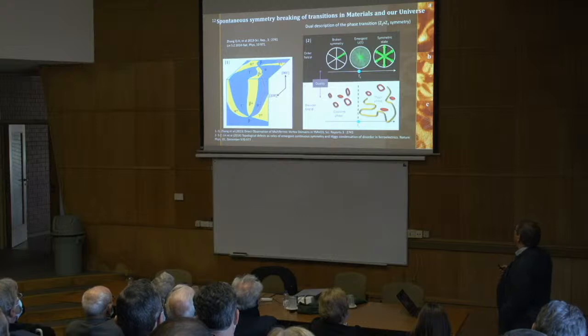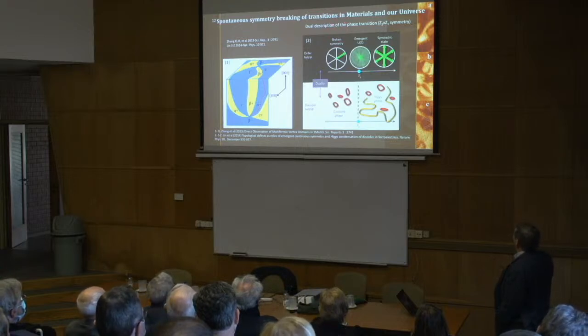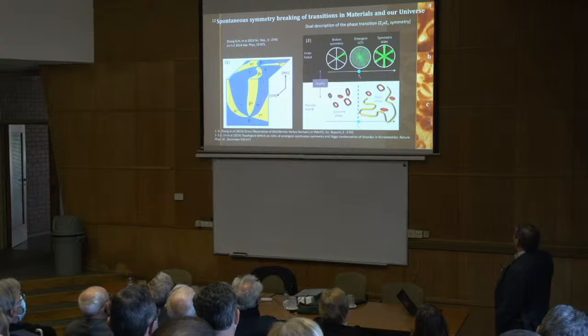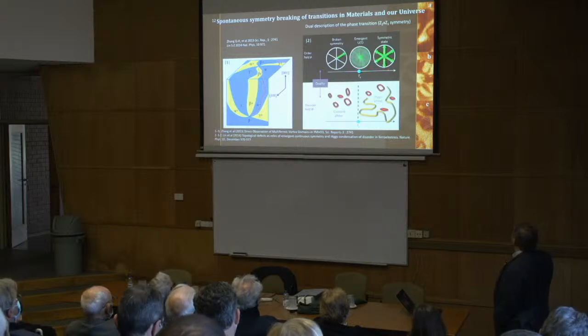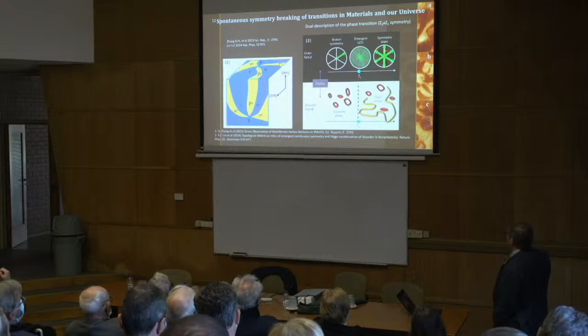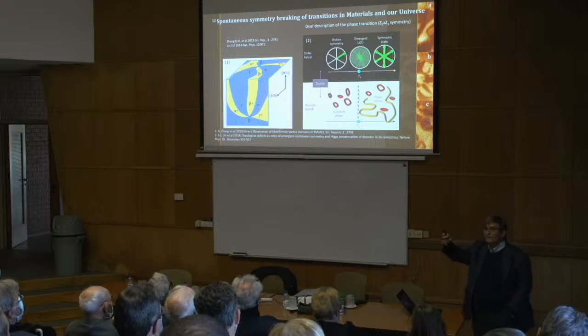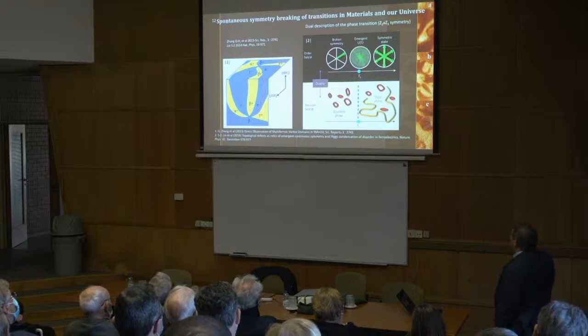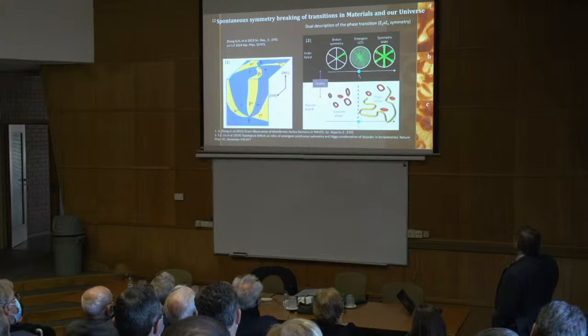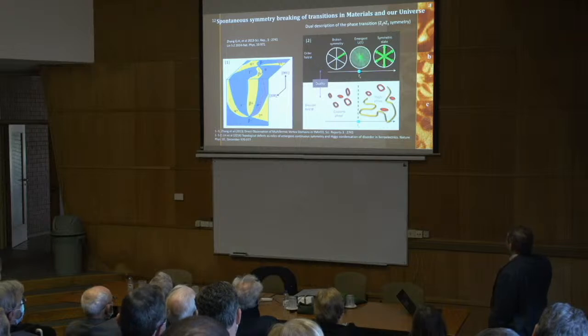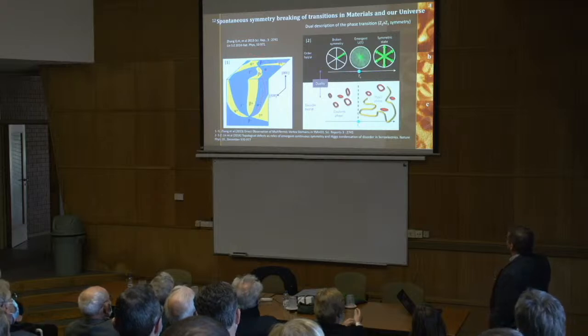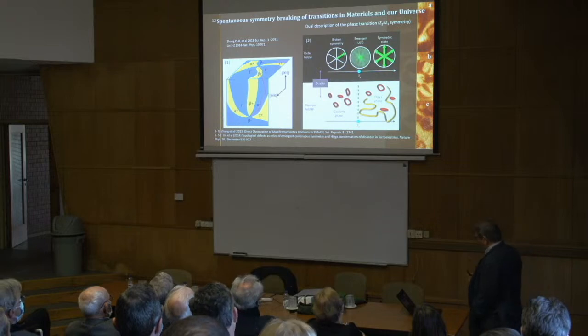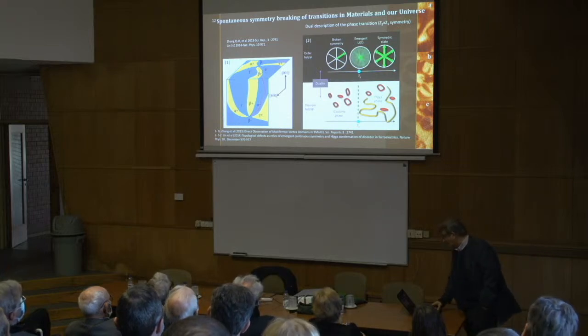What is symmetry breaking? At high temperature I have an apolar phase which is highly symmetric. Then I cool it down, and it has to decide, it has to take one of the trimerizations. By the end, all neighbors will take in sequence, we will see in sequence all the possible events, but this is a lattice. It's different from the Big Bang model, the standard equations of the Big Bang model. Really, what we observe are the cuttings of these apolar phase cores in a rather well-defined and well-crystallized polar phase. What we see are these 6-fold symmetries, 3 positive, 3 negative, with the trimerization split. In that case, the ferroelectric and antiphase boundary coincide, the 2 energetics. Okay.